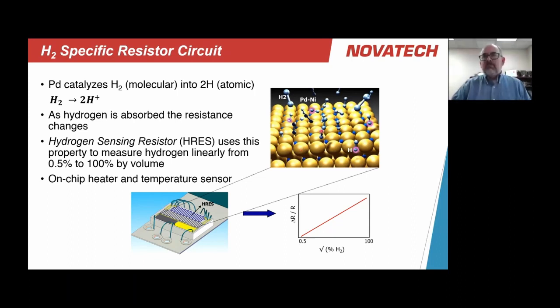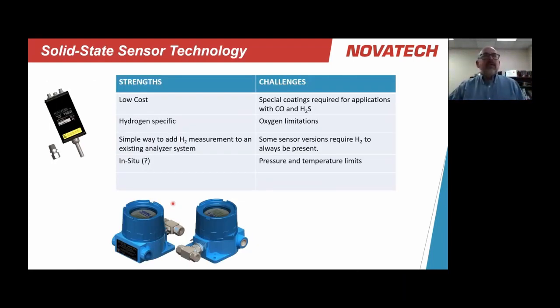surface. And so this matrix, if you will, this palladium nickel alloy, is mounted on a chip, and that can then be adapted into a form factor that's useful for our purposes of doing a process gas measurement. And they look something like this. We can see them here, for example, where the sensor is mounted at the tip of a probe and potentially could be used in situ, in other words, directly inserted into the process, or they can be integrated into a flow-through device where the electronics are housed in this hazardous area rated enclosure that allows the gas to flow through it on a continuous basis and monitors the hydrogen concentration within the